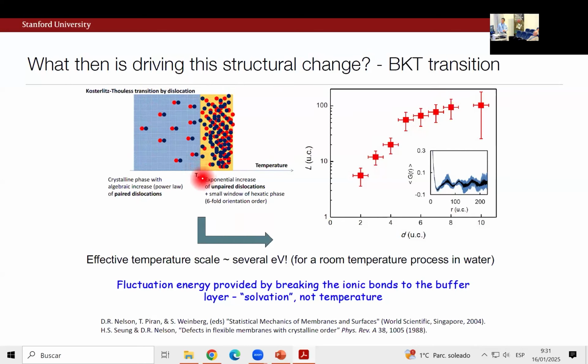But if I extract a temperature scale, a BKT kind of scale out of this problem, you get something like 1.5 electron volts, right? So why would there be this enormous energy scale in a problem when you simply put this in room temperature water? It seems so gentle. Our conclusion was that the fluctuation energies, or the effective temperature of the system, is really not coming from the actual temperature of the system, but from solvation.